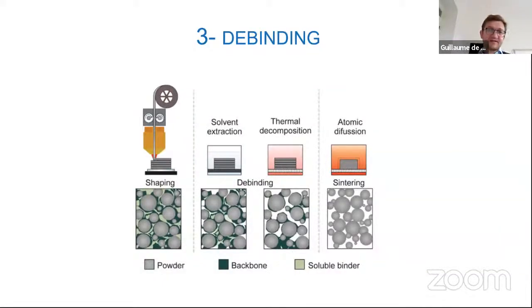Once we have a part which has been printed, we've removed it from the plate. I forgot to precise that the plate is flexible, which makes it very easy to remove the part from the plate. Once we have a part, we're going to do the rest of the post-processing, which is debinding and then sintering. So debinding is done in a two-step process. We first make what we call a chemical debinding. We dip the part in solvent, and then we do a thermal decomposition to remove the rest of the binder.